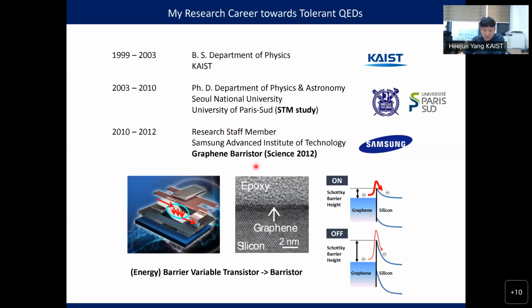This is one example. If you look at this TEM image, we clearly see silicon atoms, but we don't see graphene because this is only one atomic sheet. But you don't see silicon oxidation here. Native silicon oxide is not visible because graphene as a 2D material passivates well the silicon, which is very reactive to oxygen.